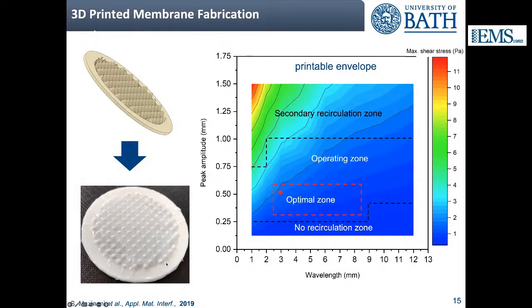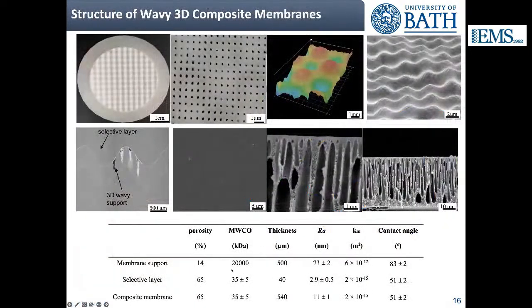And at the bottom left, this is the final membrane we get, where you can see that you have a PES selective layer on top of the 3D printed wavy support, and that the PES makes a conformal coating with the printed wavy support. So we did a bit of characterization. At the top left, you have the 3D printed support. On the top right, you have an SEM micrograph of the PES layer on top of the 3D printed support. And you can see that the PES layer forms a conformal coating onto the 3D printed support, even acquiring its underlying roughness.